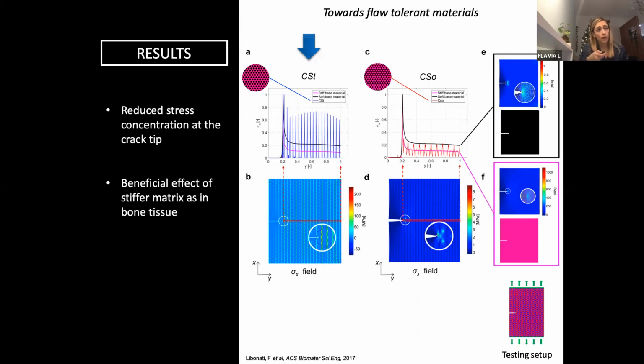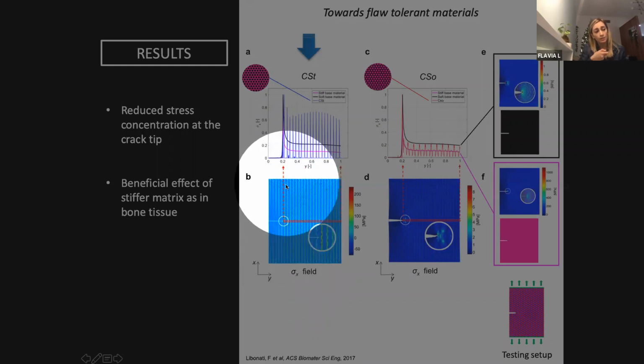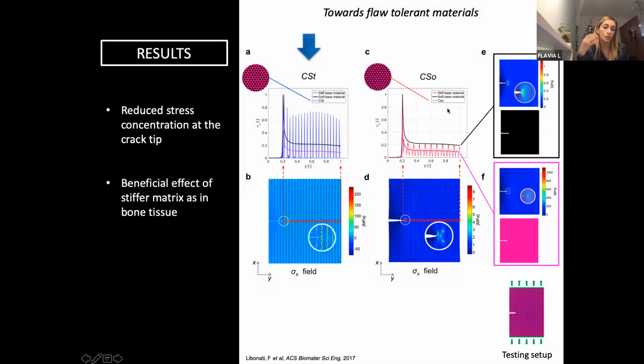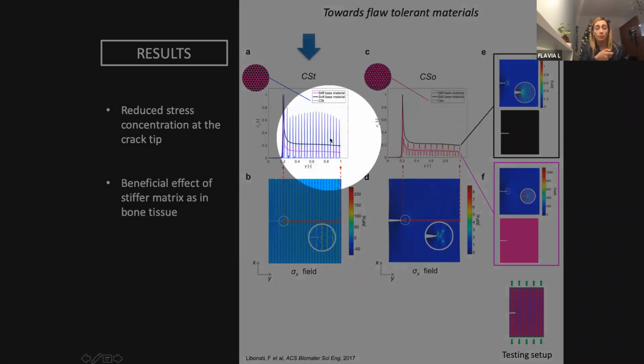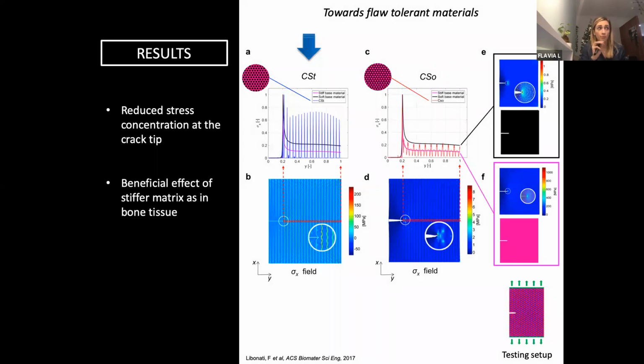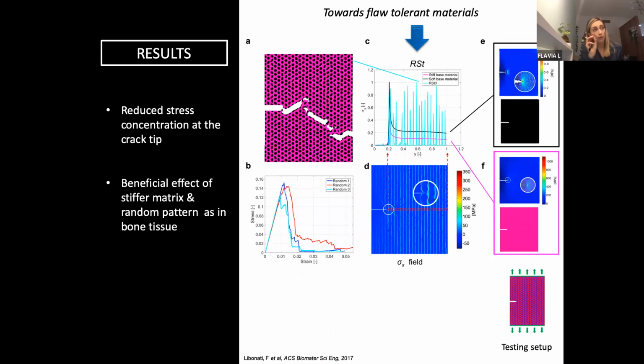But what is interesting is that if you look at the stresses, so sigma x is the stress in the vertical direction, you can see the stress field plotted through this tiny line, averaged through this tiny line, from the crack tip to the far field. What you can see is that you have a clear trend for the homogeneous material with a clear stress concentration, which is typically predicted by fracture mechanics. But the difference is that with stiff and soft matrices, in both cases you have this heterogeneous stress field, but once you have a stiffer matrix, you have a reduced stress concentration. So it means that we can move towards flaw-tolerant material in this case, and this is better achieved if we focus instead on random distribution of circular and elliptical holes.